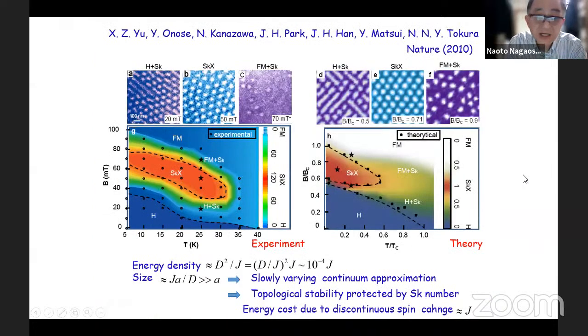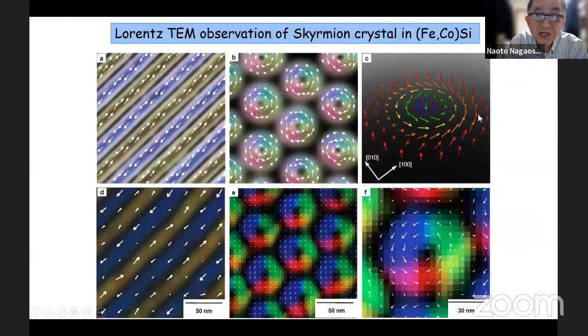And this 2D is very advantageous for the Lorentz TEM, transmission electron microscopy, so you need a thin film. The thin film is very good for observation, and also for the observation of skyrmions. So that's why we went to these materials to see the possible skyrmion crystal.